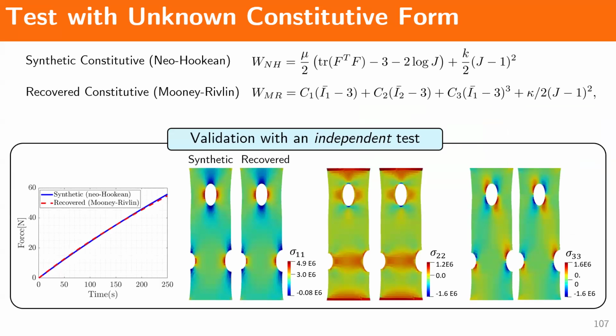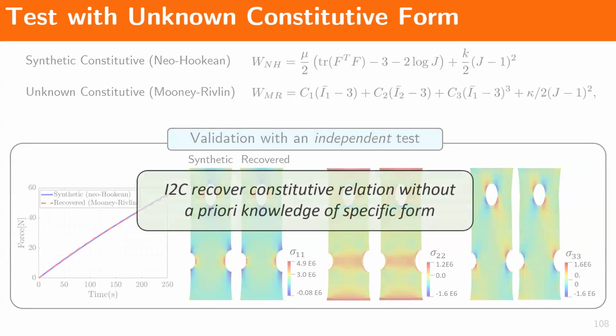So what we did here is we ran a validation with an independent test, with a different specimen geometry. We compare the boundary forces, and they match with each other. We also compare the full-field stress response, and we characterize the L2 difference of the synthetic and the recovered model for the stress field, and the errors are quite negligible for the deformation regime that we're interested in. So we conclude that the algorithm can recover a constitutive relation without knowledge of the specific model form.